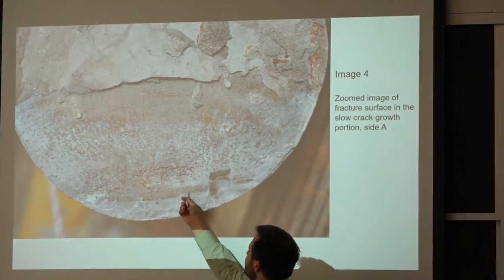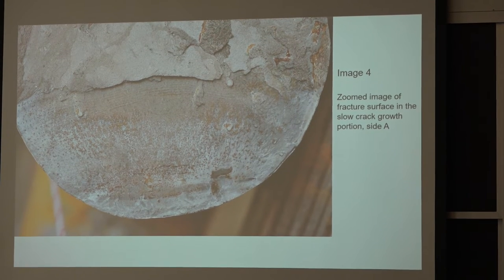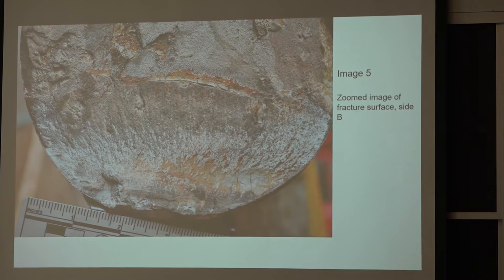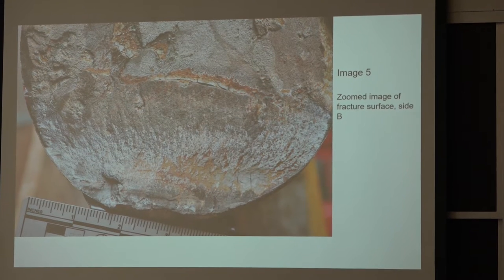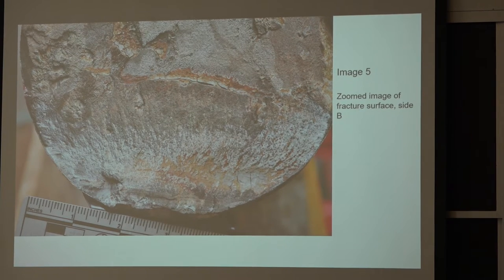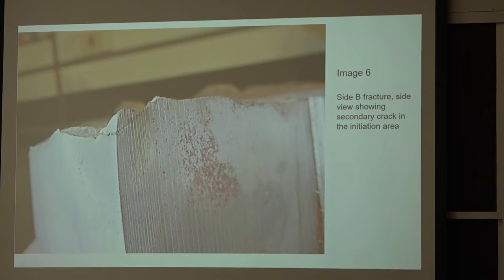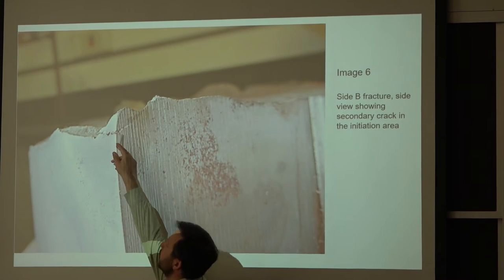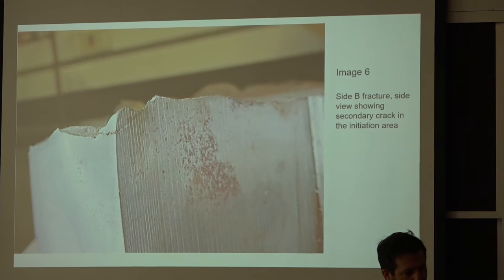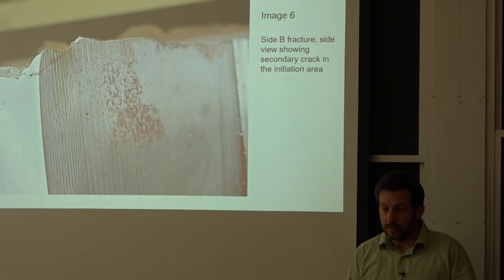So what do we do? We know it cracked slowly. It was from this area. We go and look closer and closer, different views before we get too much into the details. That was an interesting feature. Here we're looking after there was a little bit of piece cut out, and you can see that there were two cracks. A lot of times when you have branches of cracks, different cracks, it is a slow cracking process to get there.